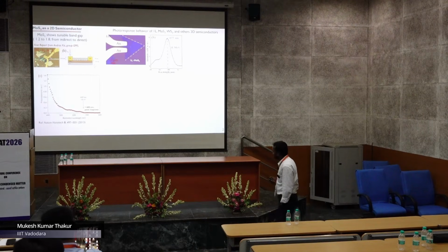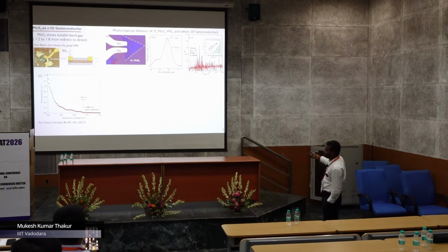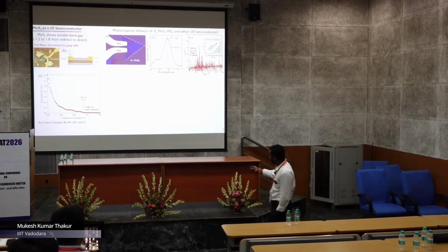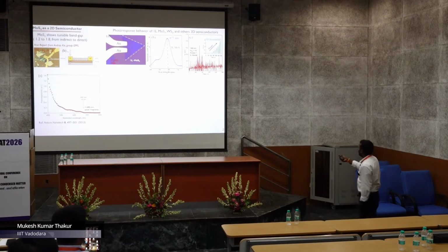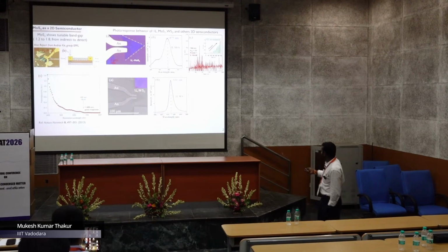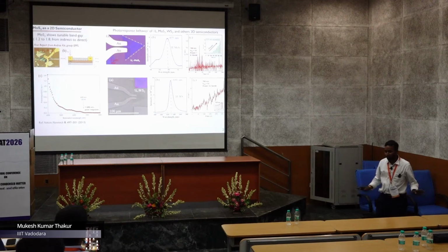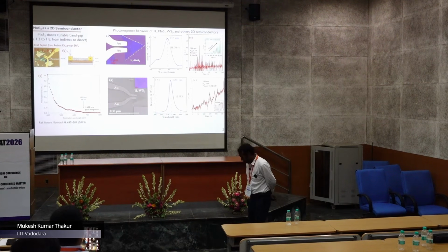Silicon goes to 1000 something. So we also tried to check whether it's true or not. We have monolayer MoS2, CVD, and we also checked with exfoliation, a very nice single layer. When we shine the 700 nanometer light, there is no response. That's true because it's not absorbing here. If you have 633 or 532, we can clearly see a very nice photo response. Similarly with WS2, we wanted to verify it. With monolayer WS2 devices, again at 700 there is no response due to their absorption. Basically they don't absorb above 680 or 710 nanometer light.